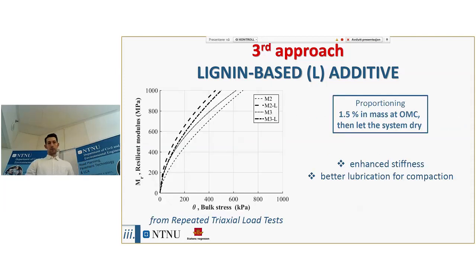Anyway, again, first and foremost, we made some preliminary investigations in the laboratory, using the Tri-axial load test, and we could understand that the lignin-based additive had a beneficial effect, since we can see that the resilient modulus is higher here than the resilient modulus attaining to the rocks which were not treated.